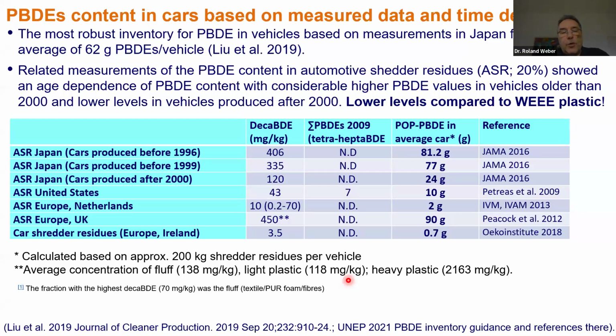So this was calculated by the impact factor given by the inventory guidance, and that has been developed from studies in Japan. So here, from this material substance flow analysis from Japan, from Liu et al. 2019, they have estimated that about 62 gram PBDEs was the average impact for cars. And they have analyzed this from car shredder residues and average content of car shredder residues. And then you can do a recalculation from the amount of the shredder with the concentration of DecaBDE. You can estimate how many grams of PBDE you have in an average car.